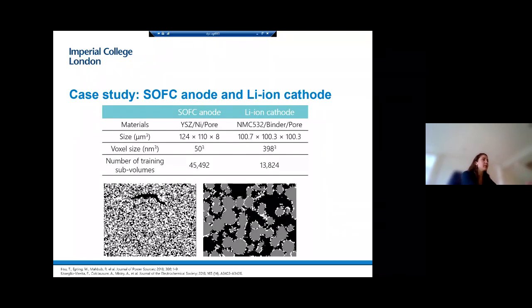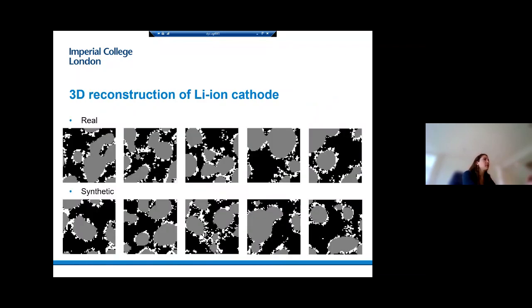they are generated experimentally in very different type of methods. But basically, we obtain this data, and we use this data that is available open source, and we use this as our training set. So the training set that we had for the solid oxide fuel cell is more than 45,000, and for the lithium ion approximately 14,000.